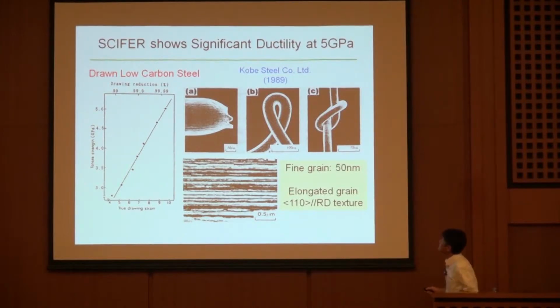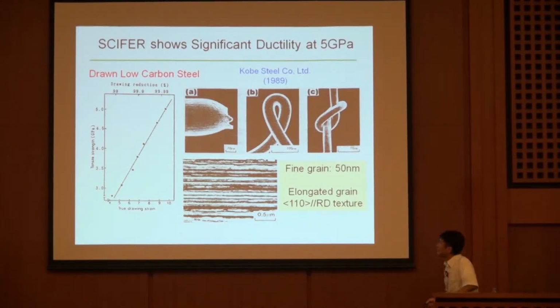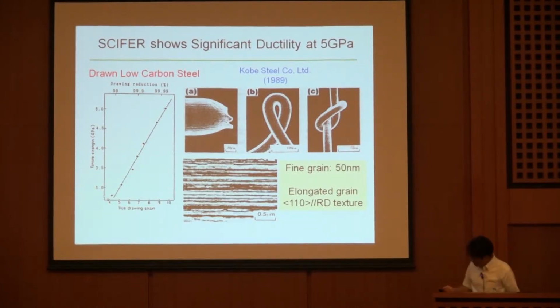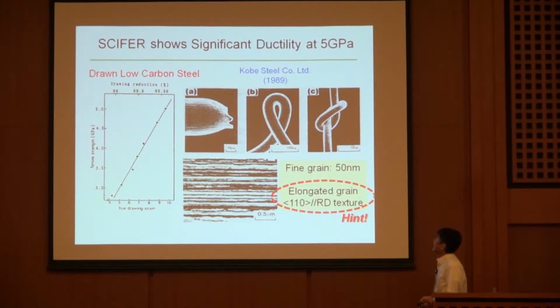When you look at the microstructure, a very fine grain, 50 nanometer grain size, has been produced by this severe plastic deformation. And grains are elongated, no longer equiaxed, and the crystallographic orientation texture shows a typical drawing texture, 110 BCC parallel to RD, the rolling direction. I thought, or actually my young colleague thought, this elongated grain structure along with the fine grain size would be a hint to obtain a high ductility.